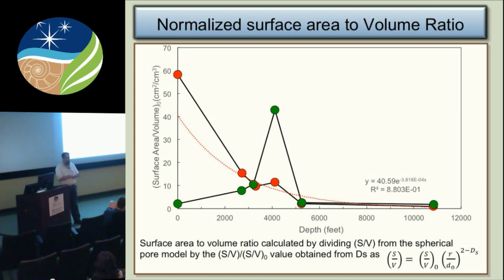We can also calculate the surface area to volume ratio. This is really important if you want to understand reactive transport, because you need to know how much of that surface is present and accessible, and how much is there to begin with. Now I've done this by combining the two data sets that you've just seen. You can take that distribution of porosity and you can calculate a surface area and a volume for that. That assumes all these smooth spheroids. So that gives you what in this equation is given as surface area over volume naught. For a given size, it gives you this smooth surface area.